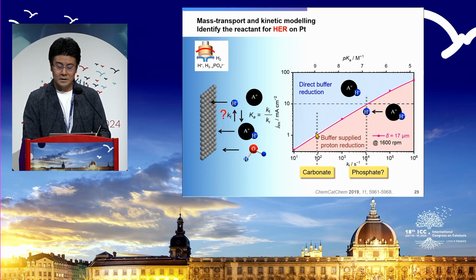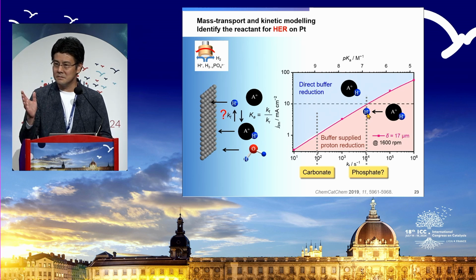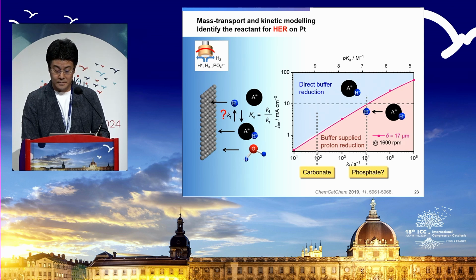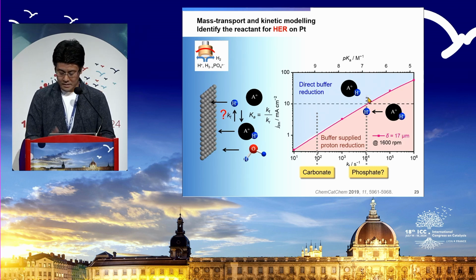Here is carbonate. So if you're using CO2 reduction or so on, and if your pH is about 9 to 10, then almost everything is direct buffer reduction. And even for the phosphate one, it is about the transition where you switch between the free proton or direct buffer, depending on the rate, the current density.